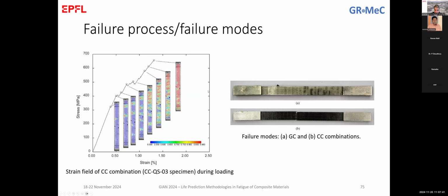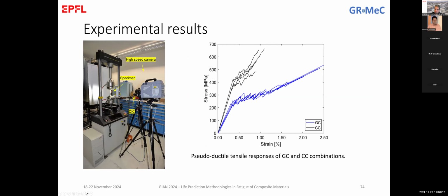Yes. So here you see also a bit of this bilinear behavior. The change in the stiffness that you can observe in the previous photos and also in this one starts when you lose the contact between the glass and the carbon, or the same when one of the layers starts failing. And this creates this damage. What is good here is that you don't have the linear behavior that leads your material to failure at a certain point without any notice of damage in the material. And this is the benefit of using these combinations to create this ductility in the system. Okay, thank you.